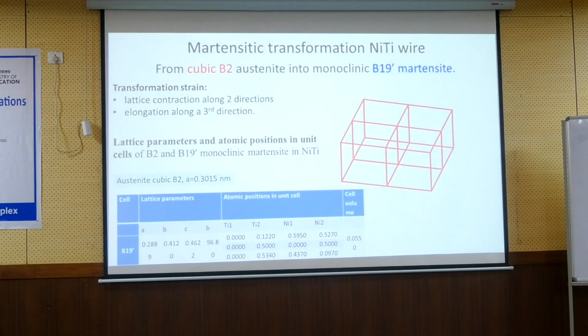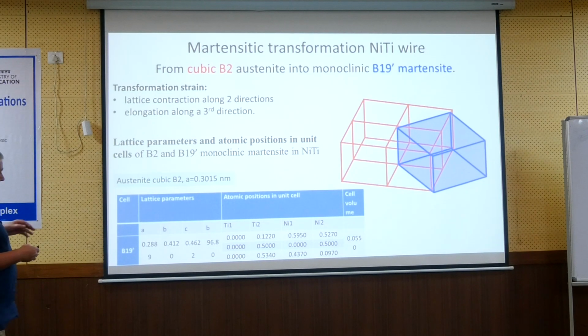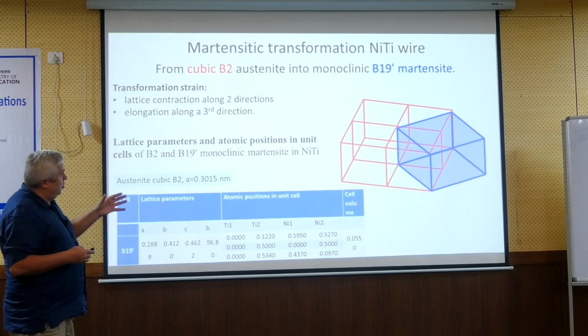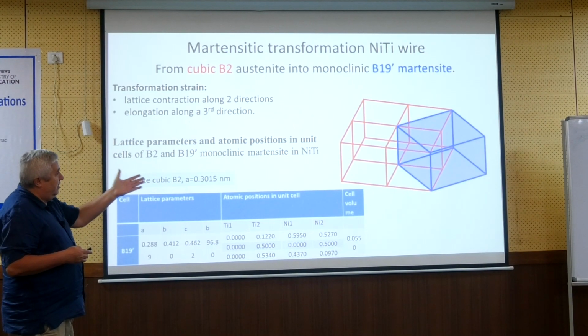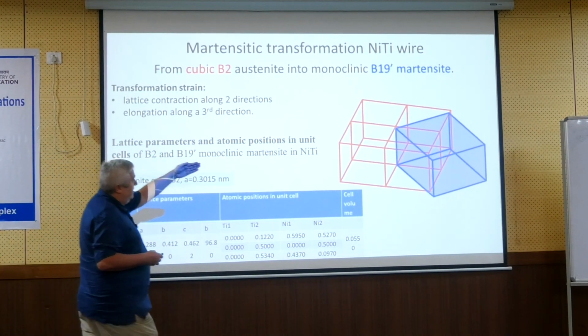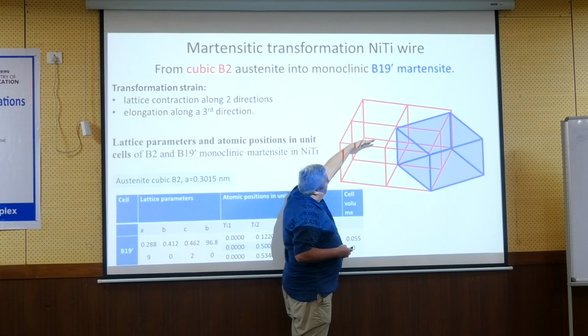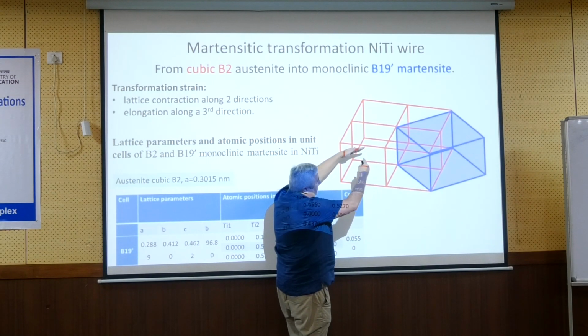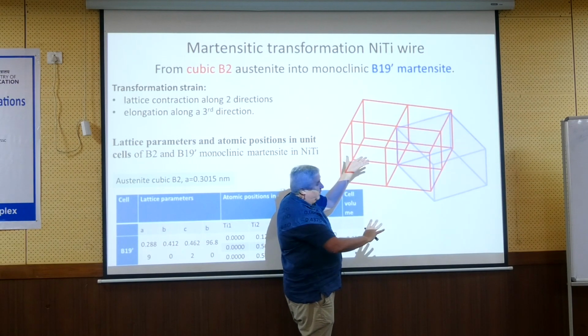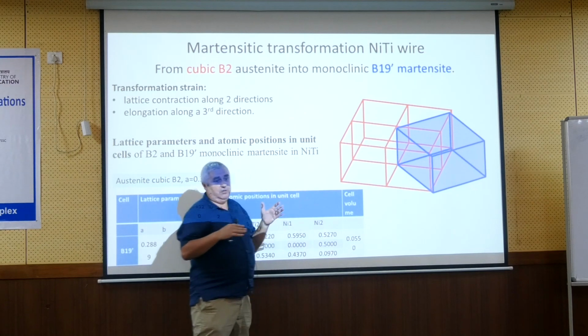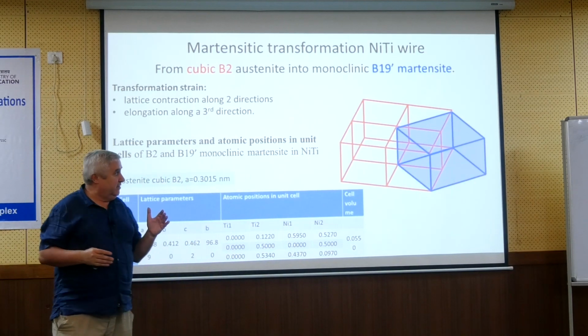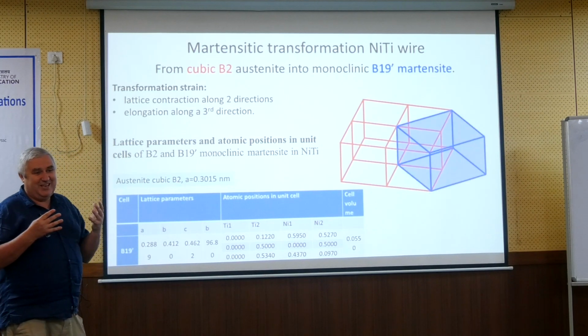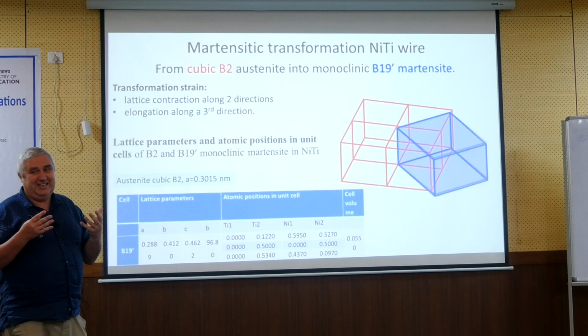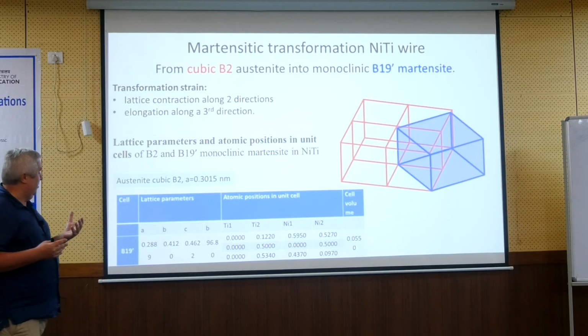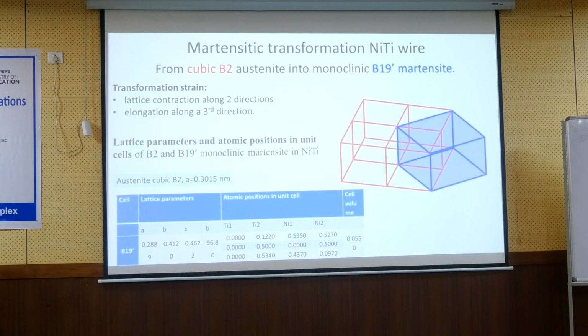This is austenite and this is martensite. And as I said, this simple animation shows how the blue martensite lattice is created from the austenite. So this is the 110 plane. You have some shortening here, expansion in this direction, and you have monoclinic distortion. This animation will play in your slides when you have it. For me, this is the best way to imagine the cubic to monoclinic transformation in NiTinol. And these are the lattice parameters.